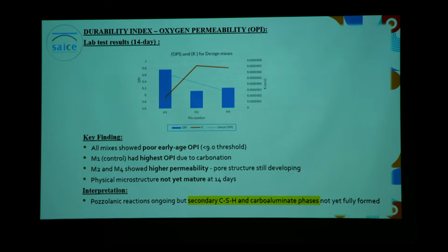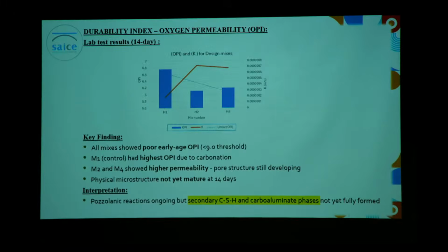And then our two design mixes, M2 and M4, with the replacement levels, showed the highest permeability in terms of OPI, due to the fact that at this early stage, the pore structure is still developing. It is still at a transitional stage. It is not yet fully matured. And then we see that the secondary cementing phases occurring here, due to the metakaolin reacting with the portlandite, are still not yet fully formed to create those secondary cementing phases and those carboaluminate phases to refine our pore structure itself.